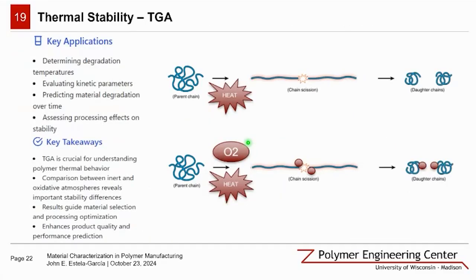So moving on to thermal stability, thermogravimetric analysis is a critical tool in understanding polymer behavior under thermal stress. It provides essential insights into both thermal and even thermal oxidative degradation processes. In polymer manufacturing, TGA in an inert environment reveals pure thermal degradation characteristics. However, the real world involves oxygen, making thermal oxidative degradation also relevant. Oxygen will lower the activation energy for chain scission, which accelerates degradation.